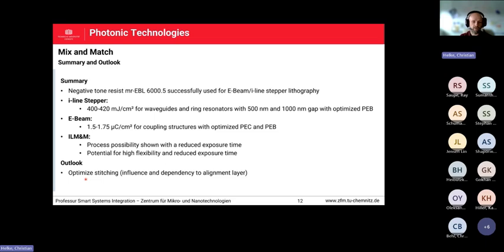The intralevel mix and match approach works quite well. So we showed here wafers with reduced exposure time, but have on the other side high flexibility to reduce the time, but also get a lot of new structures running, different versions of structures, which is just with I-line not possible in this way. And for the outlook, of course, one has to optimize the stitching, meaning the influence between 2 different exposure tools based on the alignment layer we have to align on. So the marks have to be integrated before.